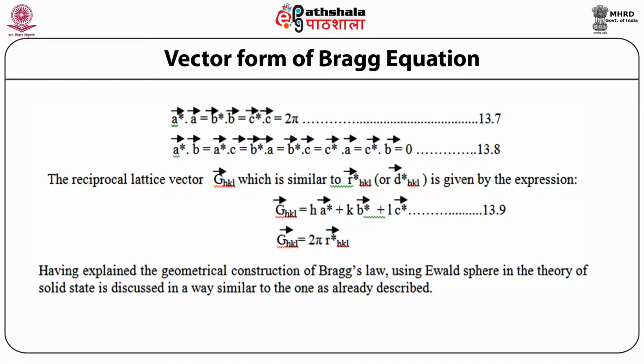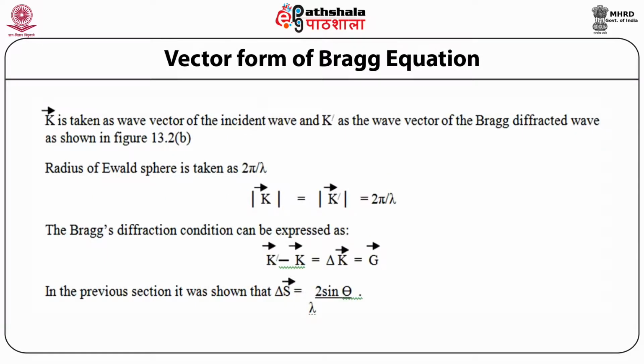Having explained the geometrical construction of Bragg's law using the Ewald sphere, in the theory of solid state it is discussed in a way similar to the one already described. K vector is taken as the wave vector of the incident wave and K prime as the wave vector of the Bragg diffracted wave, as shown in figure 13.2b. The radius of the Ewald sphere is taken as 2 pi by lambda. Modulus of K vector is equal to modulus of K prime vector is equal to 2 pi by lambda. The Bragg diffraction condition can be expressed as K prime vector minus K vector is equal to delta K vector is equal to capital G vector.